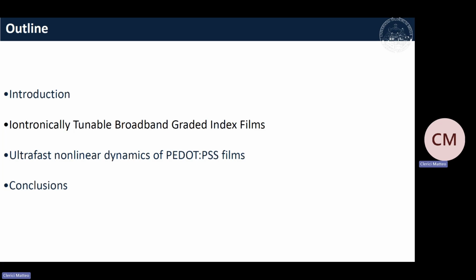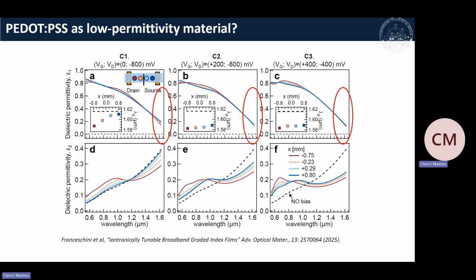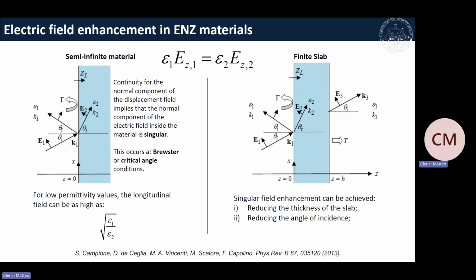And then, just out of personal curiosity, we figured that maybe because polymers generally have good nonlinearities, perhaps these materials will also have a good nonlinear response. One thing that we noticed when we extracted the epsilon was that it was rapidly approaching zero as we went into the infrared range. And we know that epsilon-near-zero materials, so materials whose permittivity goes to zero, have the main advantage of being able to enhance the electric field for free. It's just because of the continuity, the boundary condition at the interface makes your electric field go to infinity while the epsilon goes to zero.